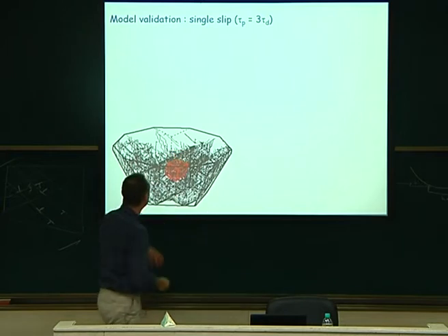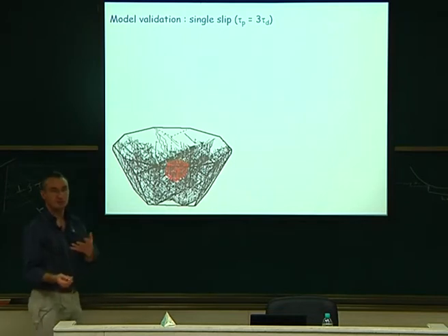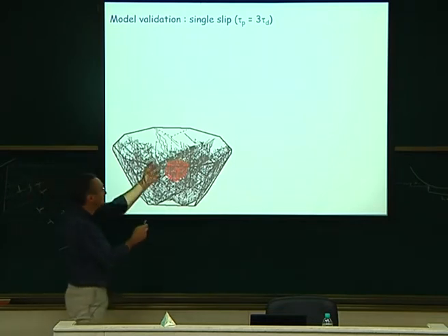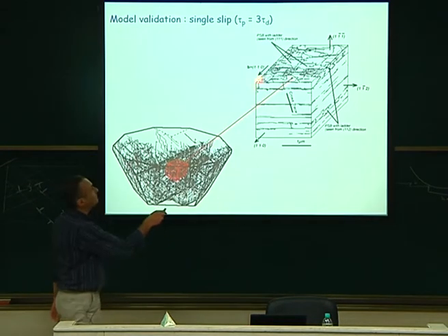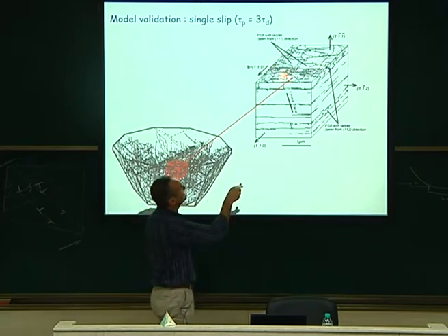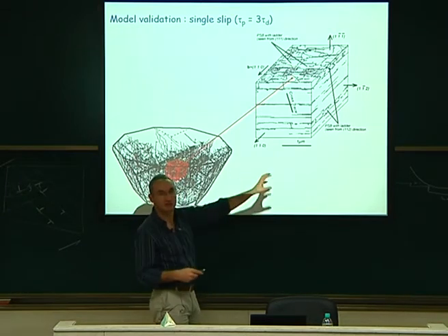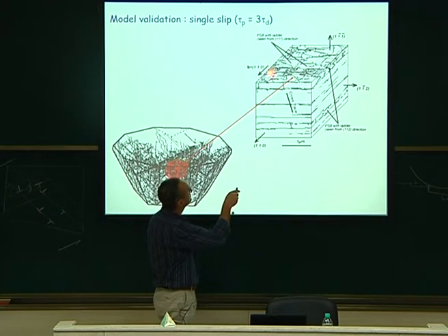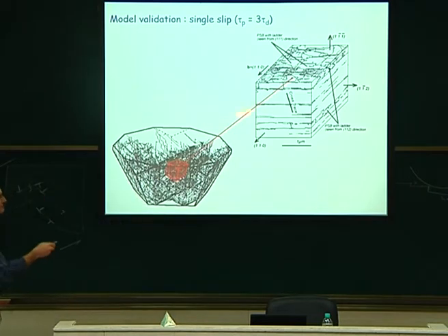And this gives this structure very quickly. If you take out from this structure a dislocation microstructure, like some experimentalists are frequently doing, from their TEM observation, this is how it looks. It looks like a very planar structure, very collinear planes like that, which corresponds to the primary plane. And inside the plane, you can see some dislocation organization into cells. You have some cells, some patterning here, which is not random. It's quite complicated. I cannot tell you why it's like that. But you can see some ladder-like structure. You have the ladders of the structure leading to a persistent slip band. It's typical of fatigue. We do see a fatigue feature here in this very planar structure.